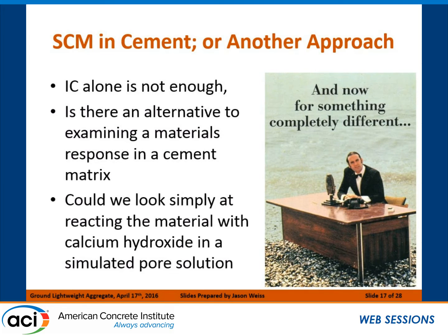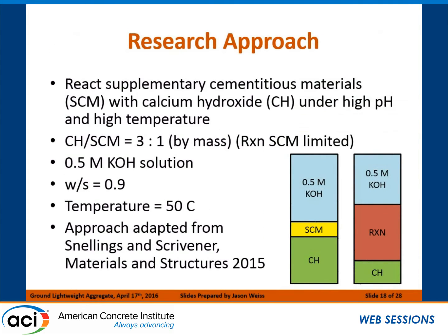One of the things that we've started doing is some testing where we're simply looking at testing calcium hydroxide with a simulated pore solution with these different materials and using this as an indicator of the reactivity of these materials that may be much faster and a much simpler test to go with. So the whole idea here is we're going to take these raw materials that we have, place them in conjunction with a calcium hydroxide, alter the pH to simulate what a pore solution chemistry would be, and use a slightly higher temperature just to try to accelerate the overall reactions. So we're going to mix the calcium hydroxide, the lime, together with a supplemental cementitious material, and then a 0.5 molar potassium hydroxide solution. We're going to do this at 50 degrees with a relatively high water to solids ratio.